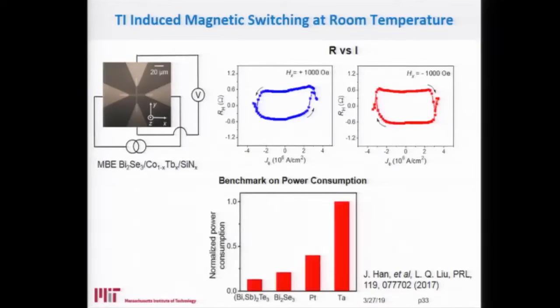What about the power performance? If you compare those topological insulators like bismuth selenide or bismuth antimony telluride in terms of energy consumption for switching each bit, we can compare them to platinum and tantalum. As you can see, there is an order of magnitude improvement in terms of power consumption. So it does lower the power required to switch those moments. The reason is the switching current is much lower, again because topological insulator has very strong efficiency in converting charge current into net spins.